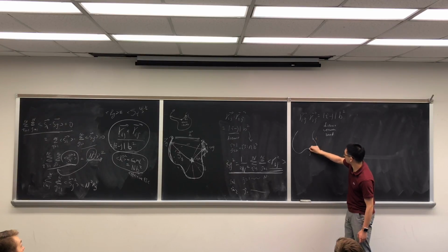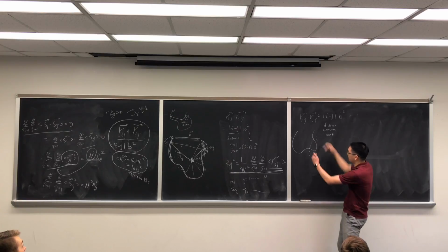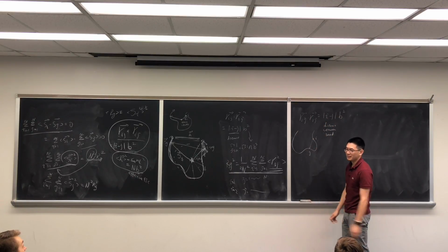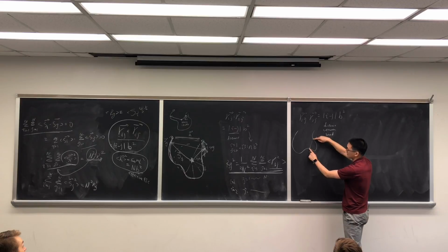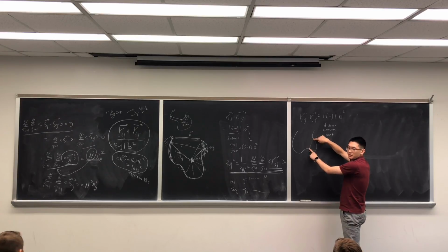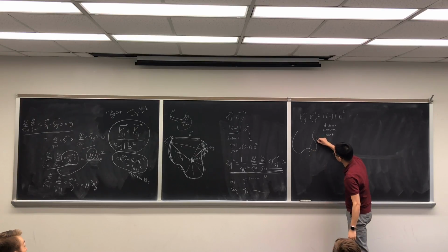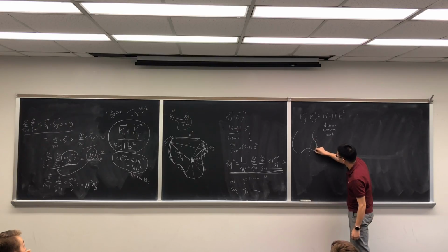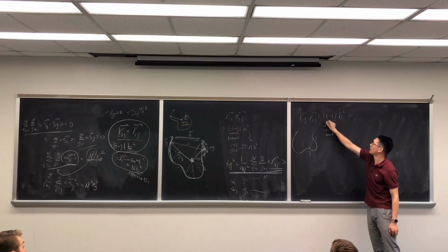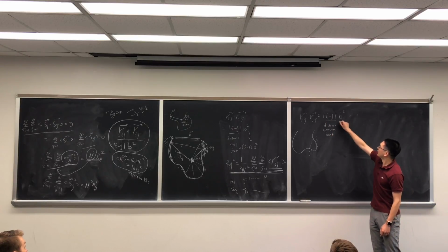Any distance between these two can be calculated like an end-to-end distance. You can consider, if you chop everything else away, it's basically the end-to-end distance for this smaller segment. It counts the distance from i to j, so j minus i will tell you how many segments there are, times b squared.